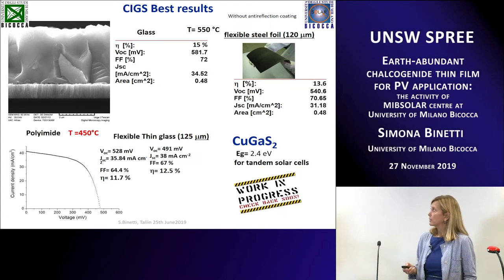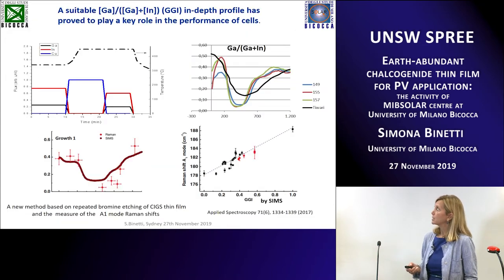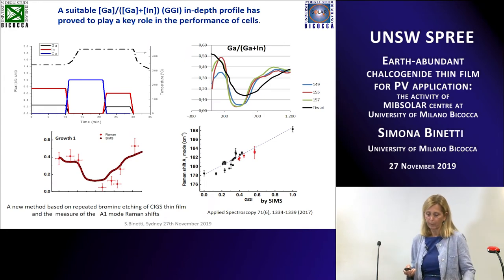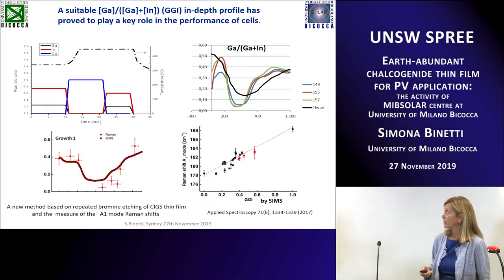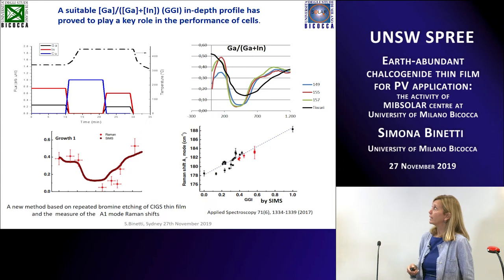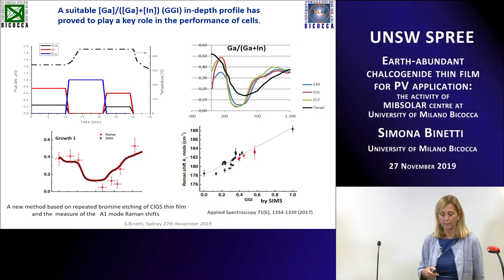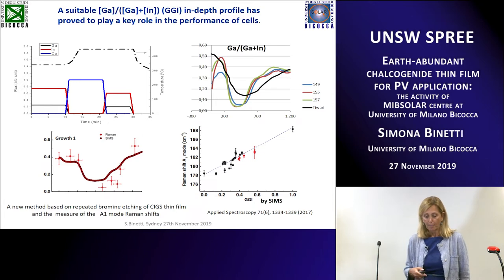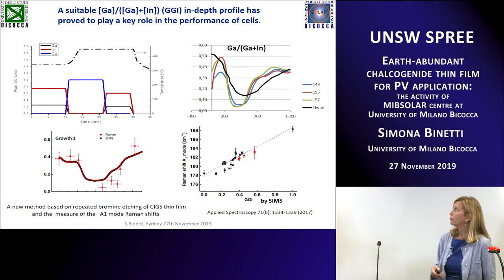By this technique, what was interesting is that it's possible to obtain the classical in-depth profile that is typical of evaporation systems, which is important to get high efficiencies in this type of solar cell. And so it's possible to have an in-depth profile of GGI that you can see is quite close to that of the record efficiencies. And this is not equal, and so maybe this can explain the fact that our efficiencies are a little bit lower than the record efficiencies.